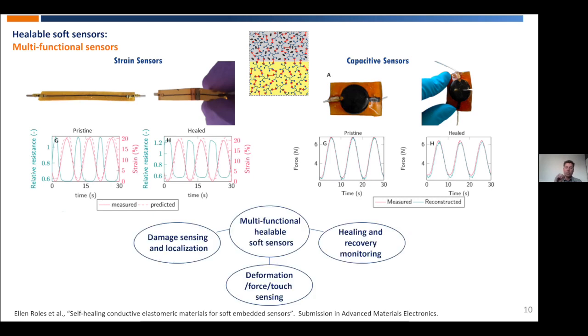But what is also very interesting is that you can have multifunctional sensors because they can be used for deformation and force or touch tracking, but they can also be used for damage sensing and localization. Because if you cut a sensor, of course, you will also see it in the sensor response. And you can also use them for healing and recovery monitoring, because when you are healing, you're actually recovering your sensor properties. So that means that you can also track the healing and see if it's carried out in the correct way. And I think this is very important for future physical and embodied intelligence, that we look at multifunctionality on the component level, but also on the material level.